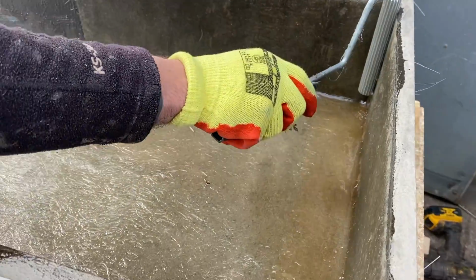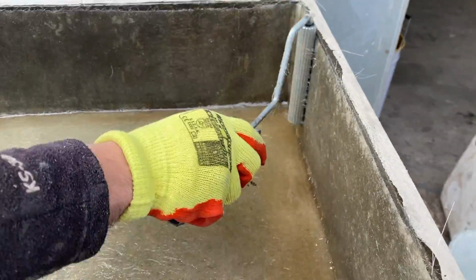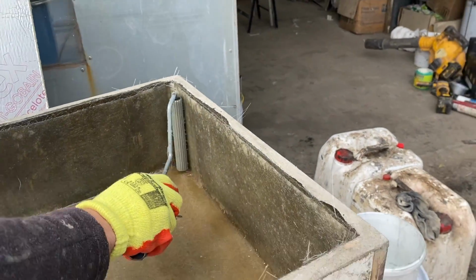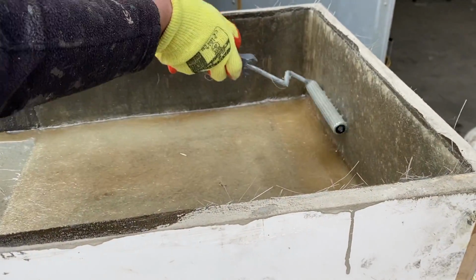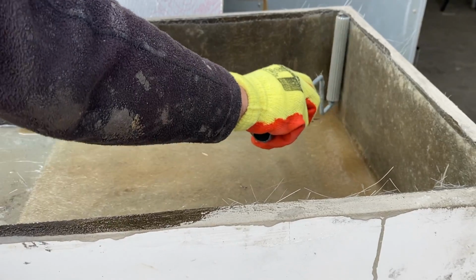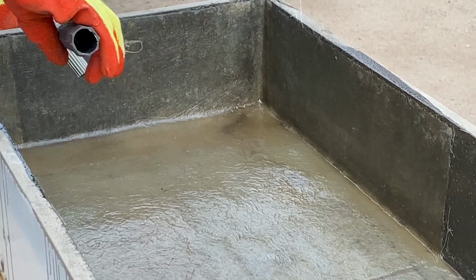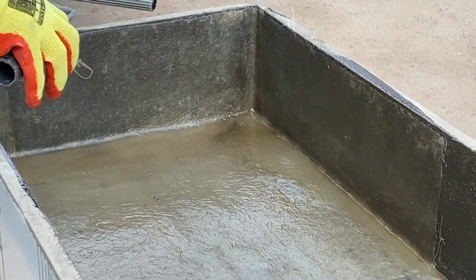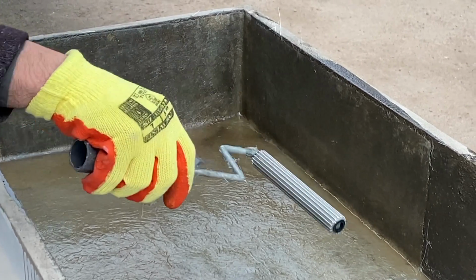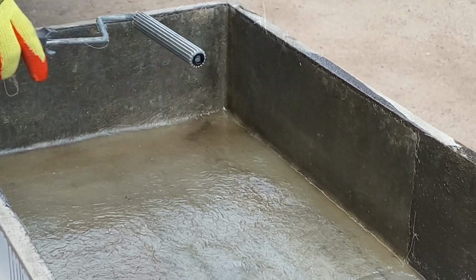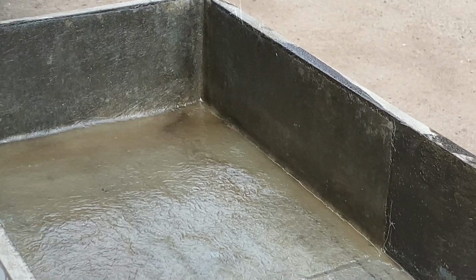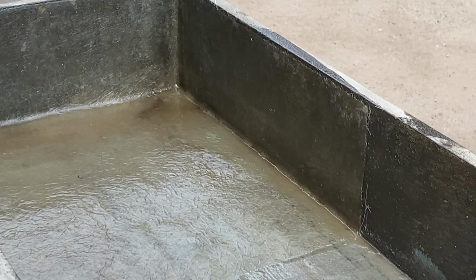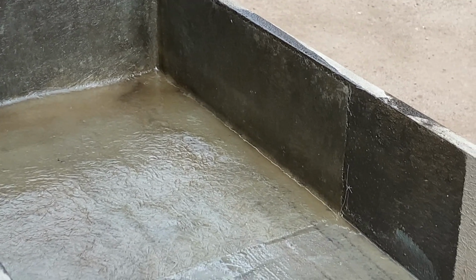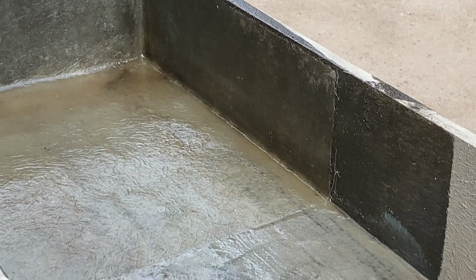As you can see, the laminate is now free of any white patches and is generally very consistent in both colour and texture. Allow the laminate to cure for a period of 2 hours or more. Once cured, carefully inspect the laminate for defects prior to applying top coat. These include exposed fibres, pinholes, splits and cracks, droplet formation, and generally insufficient coverage.